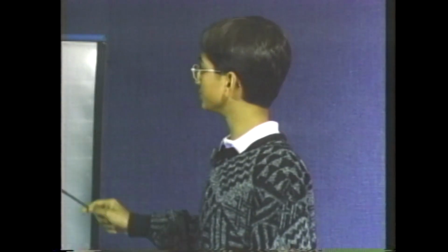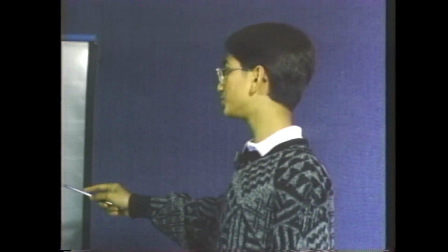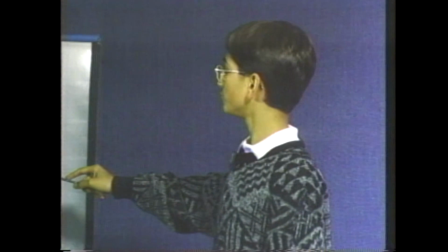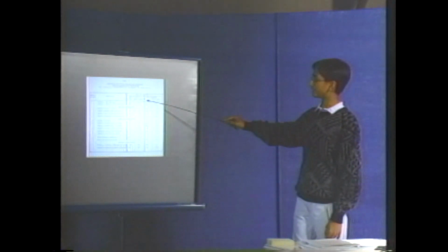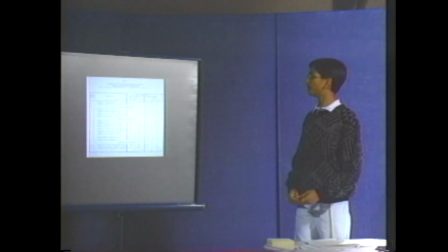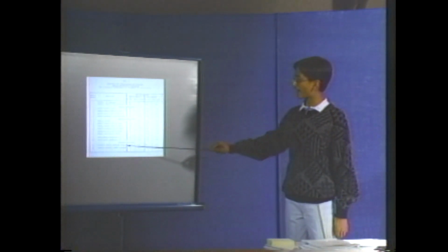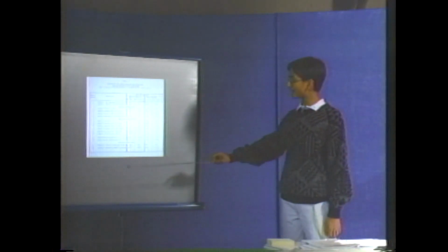The first two columns in this chart show the data that was collected before the samples were washed. Once again, the samples were divided into two sets, one set which was heat treated and the other which was not heat treated. The second two columns represent data that was collected after washing. Once again, the same two sets were tested and the results were recorded. As can be seen, the cationic surfactants as a group, represented by samples number 15 and 16, showed excellent static elimination.